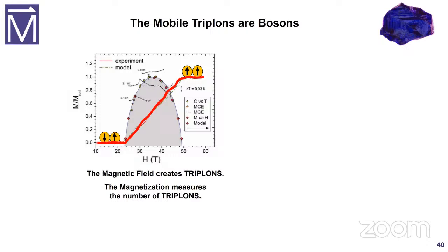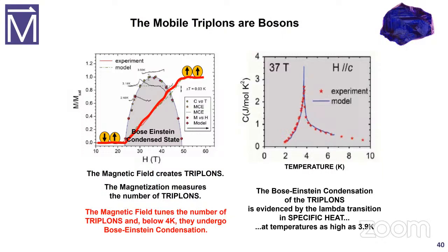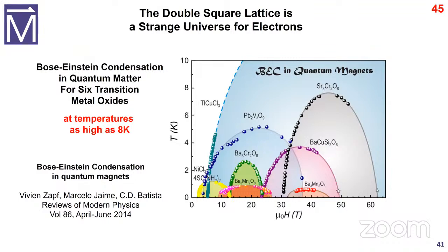Well, how do we know this is a Bose-Einstein condensate? What's the signature in helium when it undergoes the superfluid transition? It's a specific heat measurement that has a lambda shape. So we've measured the specific heat going through this transition at temperatures as high as 3.9 Kelvin, and it's a perfect lambda transition. And so this is a magnetic field that's tuning the number of triplons, and they undergo Bose-Einstein condensation, and we can measure that signature by measuring specific heat. And it turns out there's at least six transition metal oxides that are discussed in this review paper. Some of them have this Bose-Einstein condensation transition temperature as high as 8 Kelvin over magnetic fields that go all the way up to 62 Tesla.